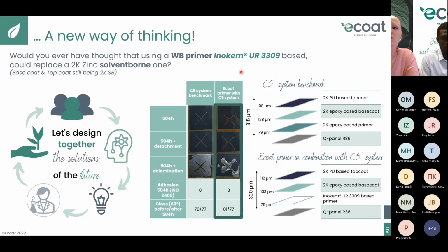Here is an example of application. We replace a 2K epoxy-based primer by a waterborne primer based on 3309. The base coat and the top coat remain the same solvent-borne C5 system. We expose that in salt spray, and the result is that we can reach same performances or even better in some case. And in the end, this system with the waterborne primer needs lower solvent rates and is safer for people.